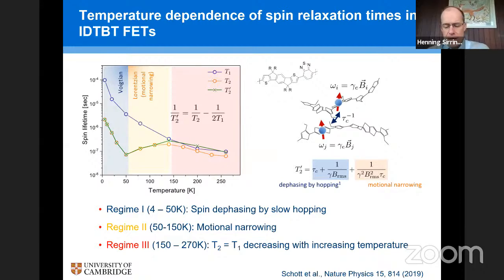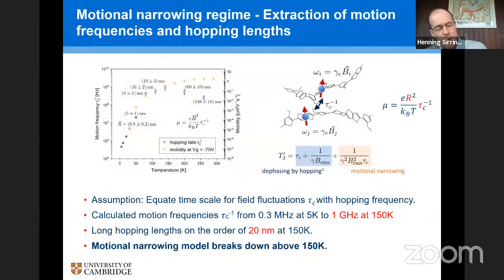And we can use this regime, as you can analyze that quite quantitatively, and basically determine hopping frequencies from the characteristic timescales for field fluctuations. And so we estimate, for example, that at 150 Kelvin, the hopping basically happens with a typical frequency of about 1 gigahertz in this system. And then you can use the measured mobility values to also estimate hopping length, and the values you get are on the order of 20 nanometers. So that's close to the length of a chain. So we know from these measurements that we can say quantitatively that charges are hopping in these polymeric systems roughly tens of nanometers every nanosecond.